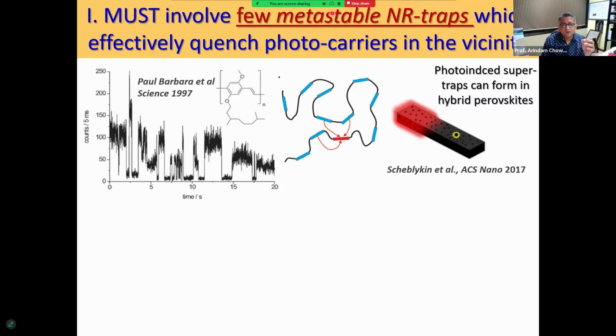For instance, this is borrowed originally from the idea in Paul Barbara's Science paper on conducting polymers, where he said that in a conducting polymer you can have many segments or chromophores. These are multi-chromophoric systems, but even then they blink, because you can have energy transfer from different segments to the lowest energy segment. An extension of this idea was used by Ivan Scheblykin, first in some nano aggregates, which I have not shown here, as well as in perovskites, where he coined the term super traps. These super traps are essentially traps that can quench the photoexcited electrons and holes non-radiatively over large zones.